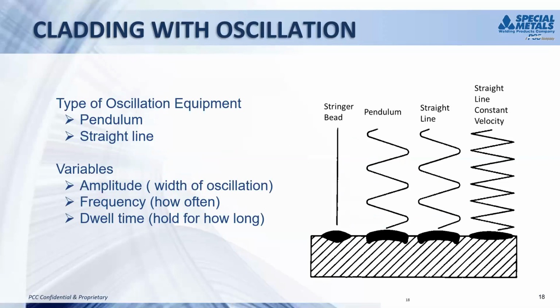The other thing, as we mentioned, is oscillation. Just be aware of the different types of oscillation equipment and make sure you're matching the oscillation equipment to your welding process. Things like a pendulum oscillator actually rotate, something like this. That works very well for gas metal arc welding because of the forgiving nature as that stick out arc gets a little bit longer. However, if you're doing something like a TIG process, as you pivot like that, you actually create a longer arc and you're changing your parameters a little bit, versus something that would be a straight line, back and forth with the same arc length the whole time.